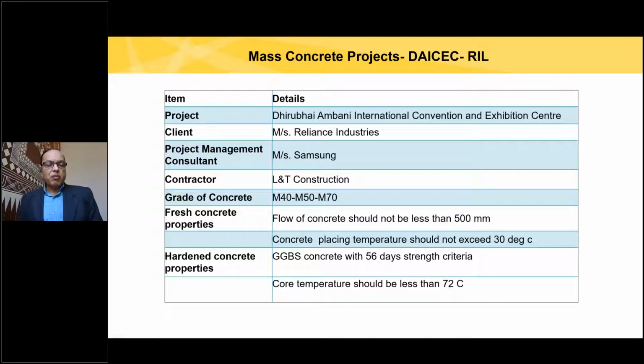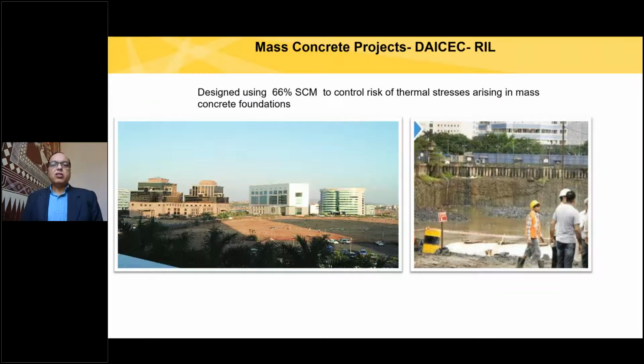And then there was another property that was required there. It is a GGBS concrete. As I said earlier, use of slag greatly benefits concrete. In fact, today you have with us Professor Radhakrishna and also Dr. L.R. Manjunatha, who is the chairman of Indian Concrete Institute. Both of them are experts in studying the properties of slag cement and concrete based on slag. Now, in this case, GGBS concrete, 56 days strength was the criterion, and the core temperature should be less than 72 degrees. Now, this Dhirubhai Ambani International project was designed using 66% supplementary cementitious materials.